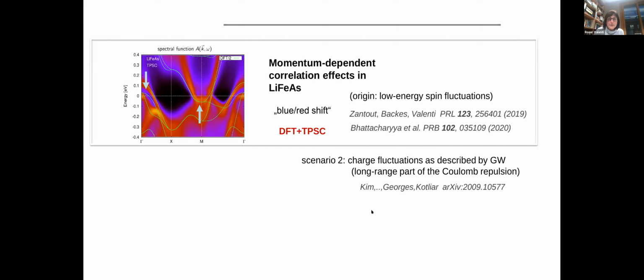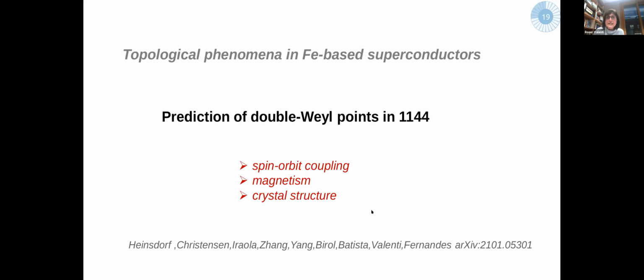Let me go now in my last 5 minutes to the topology part of my talk. And I'm now changing the iron-based superconductor I would like to focus on. So I'm going to go into the so-called 1144 materials. And what I want to show you is that by considering a combination of spin-orbit coupling, magnetism, and the very special structure of these materials, one can predict the presence of double Weyl points. Let me show you that step by step.